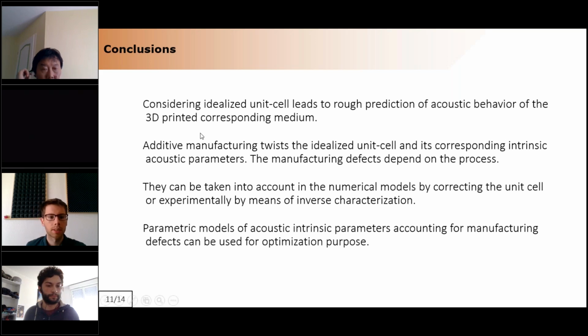To conclude, we have seen that if you just consider an idealized unit cell of your porous medium, you will obtain a prediction of its acoustic behavior that is correct, but not very precise. Because when you 3D print this material, the unit cell changes because of additive manufacturing inherent defects, and these changes of the microstructure impact the acoustic behavior of your material. Also, what we didn't say, but it's quite important, is that the manufacturing defects depend on the process. If you use plastic or metal or different techniques, you will not have the same defects, but you are likely to always have some defects.